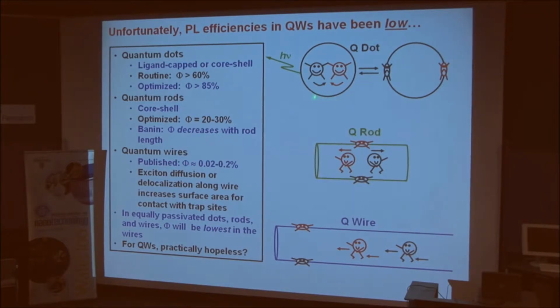And 20 years ago, early in the quantum dot field, the band edge PL efficiencies were essentially zero. All the photoluminescence was red-shifted trap emission, which meant that the surfaces were highly defective. But the passivation schemes have developed over the last 10 years or so, such that now the PL efficiencies in quantum dots are routinely 60% and above, and in rare cases approach near unity. So the problem has really been solved for quantum dots, and quantum dots are now very well passivated.